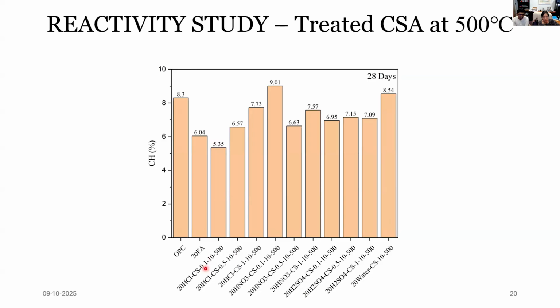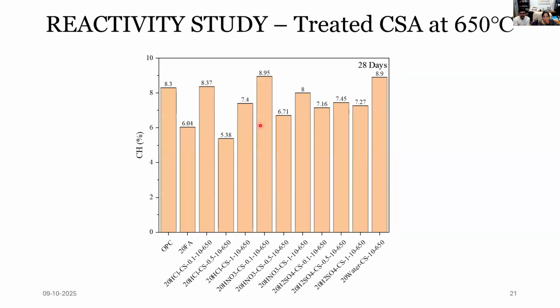However, when we increase the concentration of hydrochloric acid treatment from 0.1 to 0.5 and to 1, we could see there is a significant increase in the CH in the system, which means that even if we are using an acid with higher normality, which removes a higher amount of impurities from the system, it doesn't suggest that the reactivity will increase in a proportionate way. So we should be very cautious about using a specific acid, to understand how the impurities are getting removed and how it is affecting the reactivity. Similar to this, we use ashes which are calcined at 650 degrees centigrade. We could see there is a difference in the way in which the system is getting reactive and how well the CH in the system is consumed.